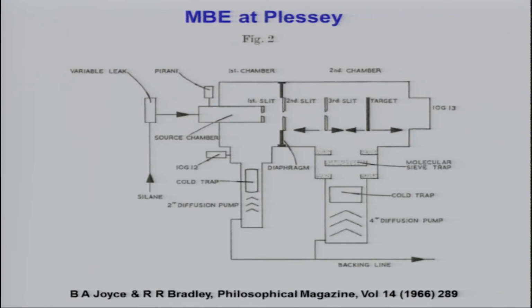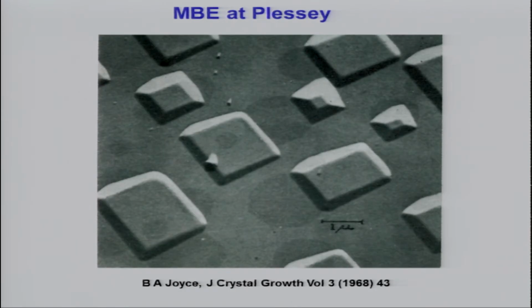So this was, from my point of view, a very early example of growth from a molecular beam to produce a semiconductor film. Here you can see silicon islands grown on the silicon substrate. They're clearly epitaxial, as you can see from this picture. So this is long before we were working at Mullard's.